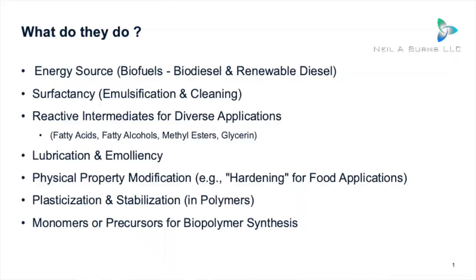Plasticization and stabilization in polymers: oleochemicals like epoxidized soybean oil, or ESBO, are used as plasticizers and stabilizers, particularly in polyvinyl chloride, PVC. Plasticizers increase flexibility and stabilizers prevent degradation. Finally, monomers or precursors for biopolymers: it's an emerging, still small area. Dicarboxylic acids like azelaic acid or sebacic acid, along with diols and polyols, are polymerized to create bioplastics or bio-based polymers such as biopolyamides and polyesters — a niche area with a lot of active research.